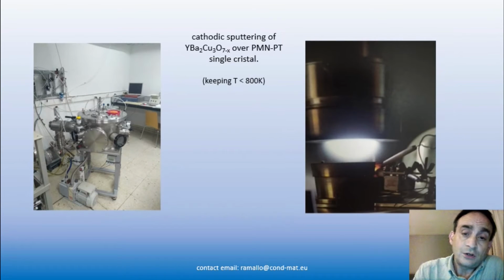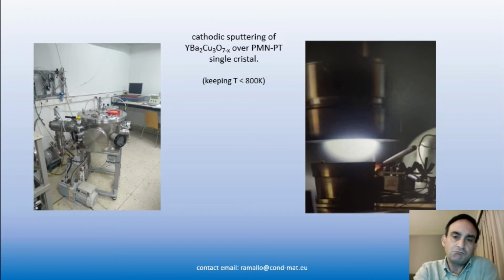To grow these films over PMN-PT is not very different from growing over strontium titanate. The crystallographic unit cell lengths are quite similar. We do that by cathodic sputtering deposition.